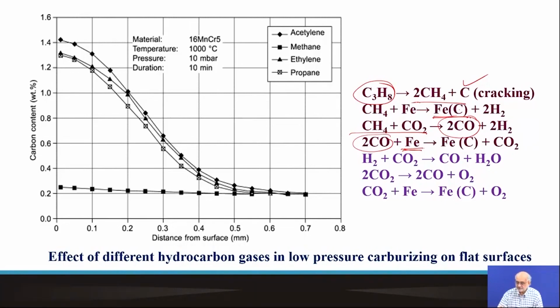So these gaseous byproducts, they escape. So they are not much of any consequence. But since there is a hydrogen evolution, we have to use a closed lid, closed chamber, and also have the possibility of burning out the gas discharge from this reaction chamber. So carbon gets adsorbed to the surface, and that's basically how we have carbon enrichment or case formation. We also can have a parallel reaction of formation of carbon dioxide leading to formation of carbon monoxide, and in turn carbon dioxide can release carbon by way of this kind of a reaction.